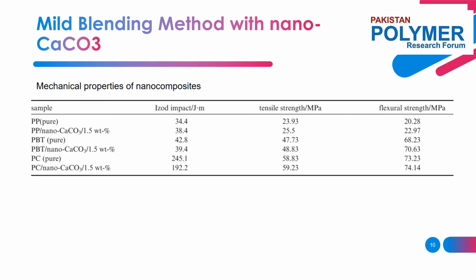Thermal degradation didn't occur even if water was introduced into the melt. Especially compared to neat PP, the Izod impact strength and the tensile strength of the PP and nano calcium carbonate composite showed a substantial increase with the addition of only 1.5 weight percent of nano calcium carbonate particles. It suggested that inorganic nanoparticles with a good dispersion state, obtained by the mild mixing method, can play an important role in improving the strength and toughness of PP.